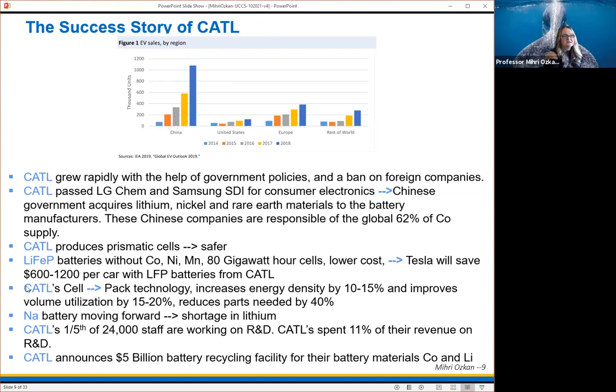And another critical decision was that CATL moved from cell technology to pack technology, and this increased the density by about 10 to 15% and improved the volume utilization, again, by about 15 to 20%. And this also reduced the parts needed by about 40%. So this was, I think, a great move. And now Tesla is trying to adopt this, and they are learning and talking with CATL. And recently they started moving into sodium batteries, moving away from lithium, thinking that a shortage in lithium